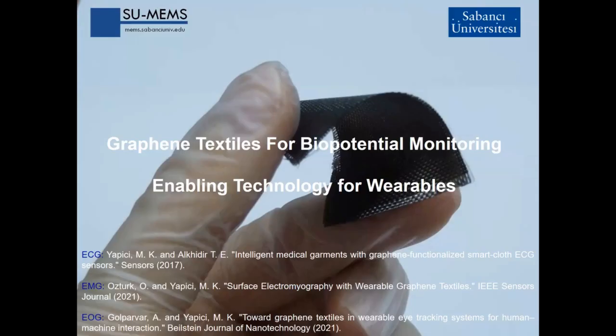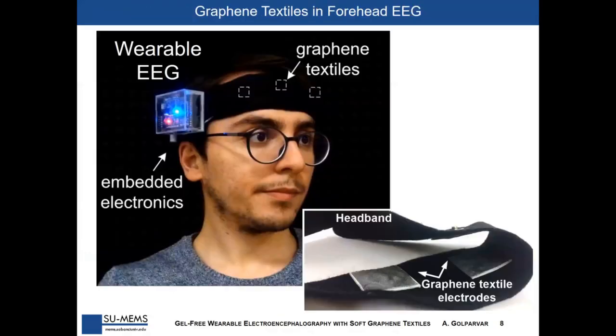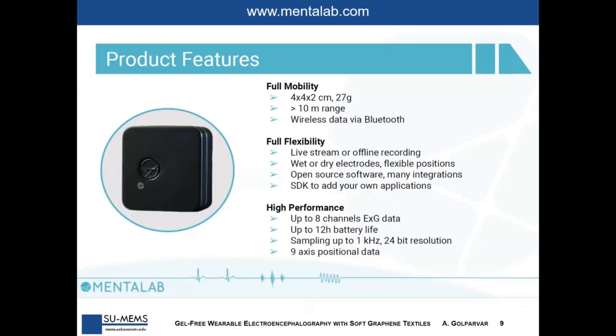on the skin surface. Our group already reported the successful acquisition of cardiac, muscular, and ocular biopotentials with this fabrication methodology. For EEG, we only used hairless locations on the skull in this study, since textile electrodes are well known to perform best in less hairy sites. Forehead EEG is the best fit here, where active electrodes are at FP1 and FP2, and the reference is at FPZ. We are delighted to use Mentalab's data acquisition unit in this study instead of our custom design system. Mentalab offers a compact and portable device and targets mobile EEG applications.